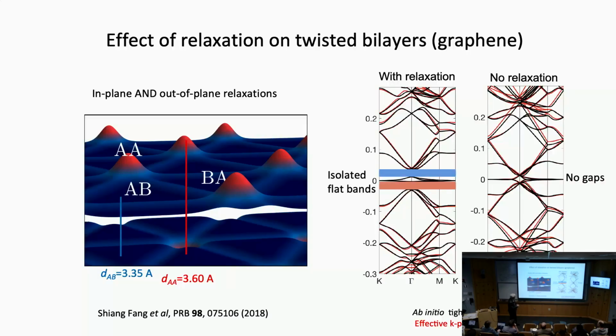So this exists in theory, but it also exists in experiment. There's no gaps without relaxation, and I also mentioned that in the simple continuum model, or à la this type of MacDonald, there's no gap. The reason for this importance is that it separates the flat bands from the rest of the states. And this separation actually gives us some level of understanding, the detailed understanding of what the geometric effects in the